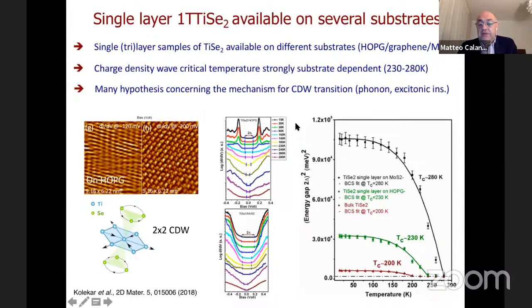the critical temperature changes. So, for example, this is the case of the bulk. Bulk titanium diselenide has a critical temperature around 200 Kelvin, slightly less, I think 197 or something like that. But then, if you put a single layer on HOPG, then the gap, this is the charge density wave gap that is measured here by STM, closes at somewhat higher temperature, around 230. And if you put it on molybdenum disulfide, closer to 280.